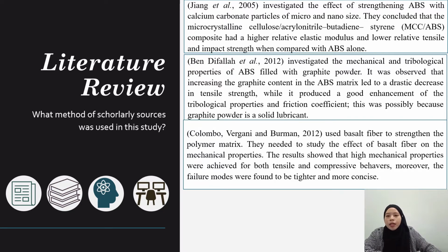Next, according to Ben Difallah et al., 2012, who investigated the mechanical and tribological properties of ABS filled with graphite powder, it was observed that increasing the graphite content in the ABS matrix led to a drastic decrease in tensile strength, while it produced a good enhancement of the tribological properties and friction coefficient. This was possibly because graphite powder is a solid lubricant.